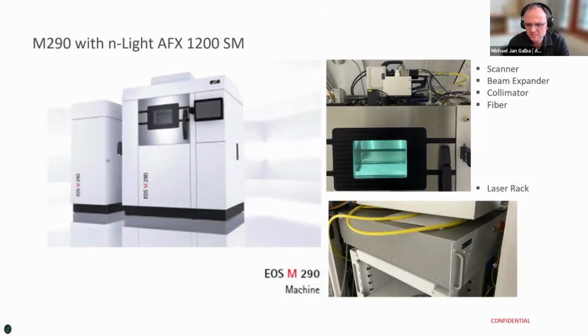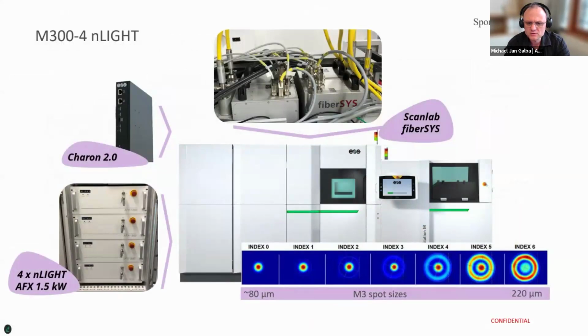And therefore, one of the first systems where we have applied beam shaping was with our partner nLIGHT, together to equip the M290 system with a 1.2 kilowatt AFX laser of the company nLIGHT. That laser provides you the possibility to change within milliseconds from a Gauss beam into, for instance, a ring mode, a multi-mode laser profile. We've additionally also equipped our M300 system with the latest scanner technology, as well as with 4 times 1.5 kilowatt laser energy, and we have just unleashed like 6 kilowatt of light into a very small process chamber.